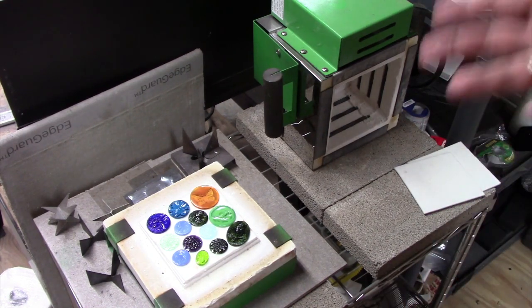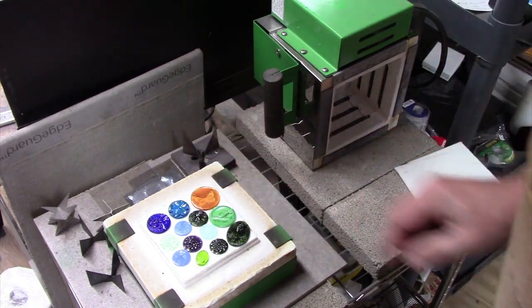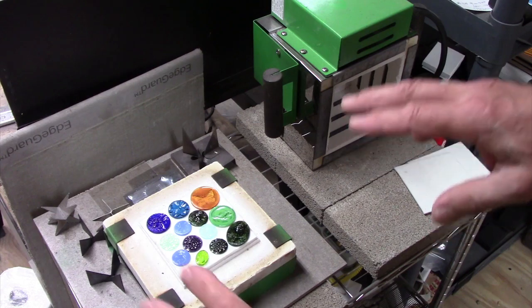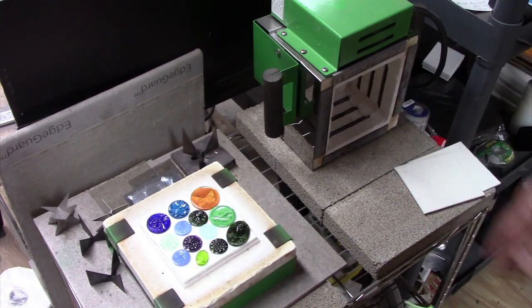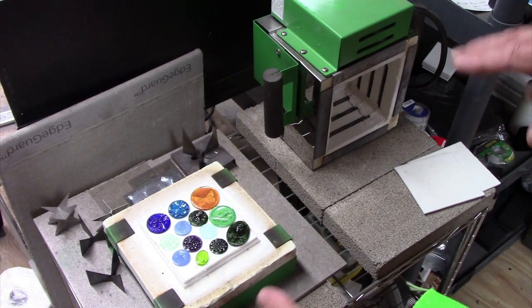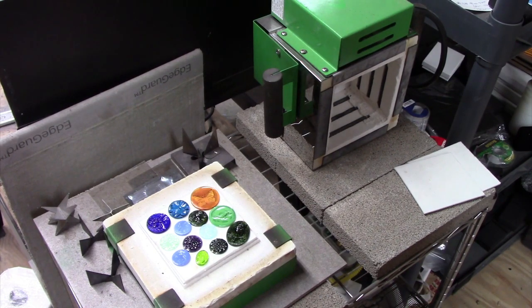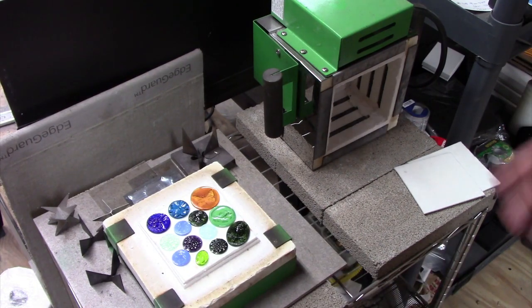There are very, very specific schedules for these things if you were going to get into this. But I'm just going to raise the temperature very slowly to about 950 degrees. Then I'm going to hold it there for about half an hour, 45 minutes, because everything in here is much less than a quarter of an inch thick. Then I'm going to turn down my rheostat, my little control module, to what I know is about 800, and let it cool for another 45 minutes to an hour to 800. That'll be about the strain temperature, which is below that. It probably won't be affected by the change in temperature.